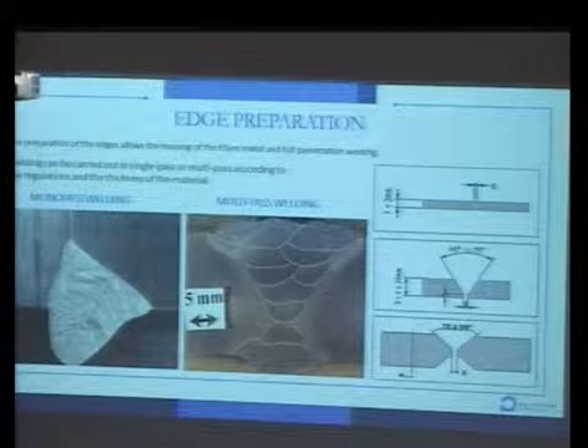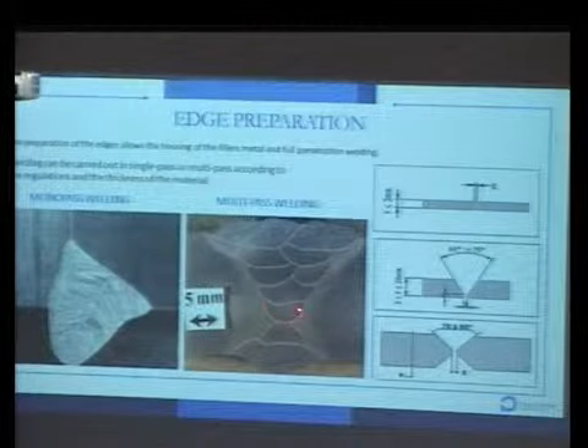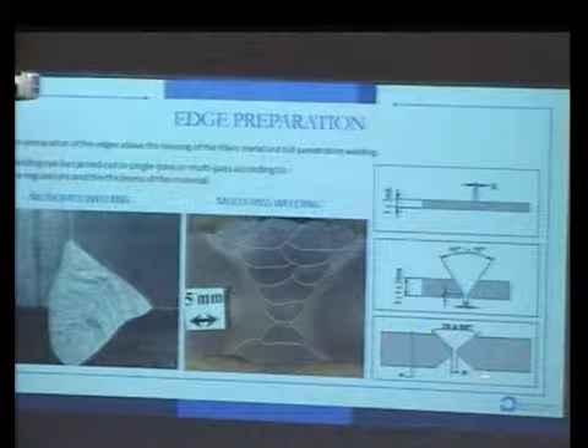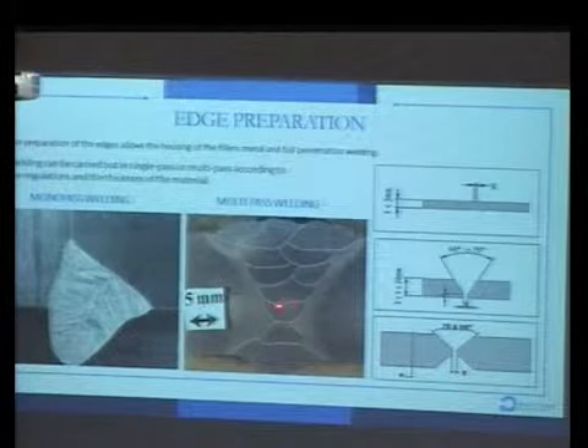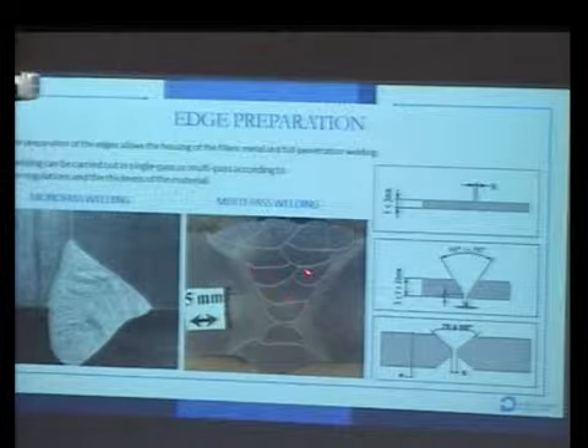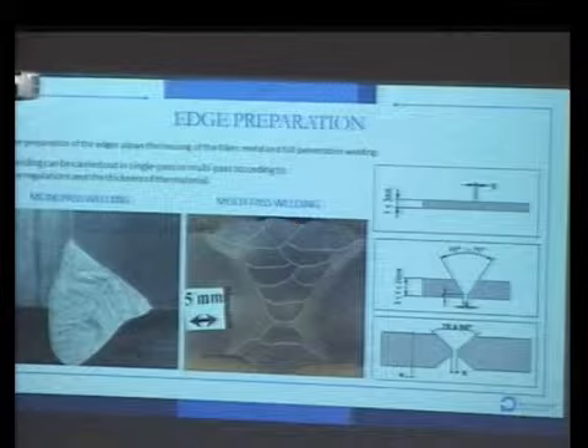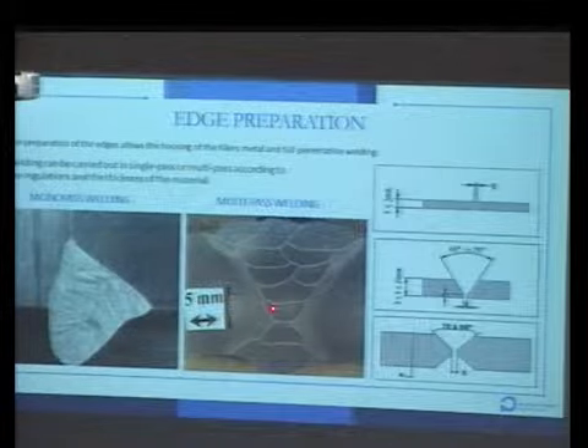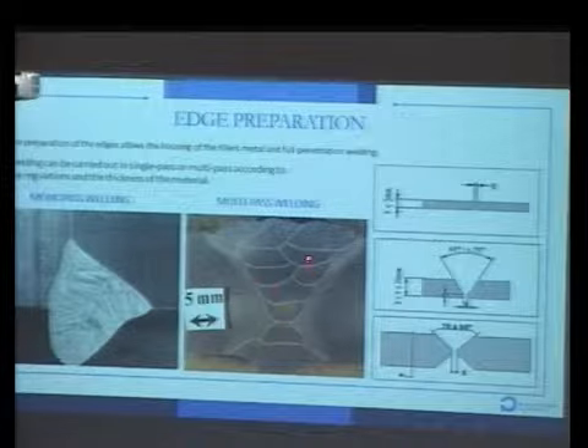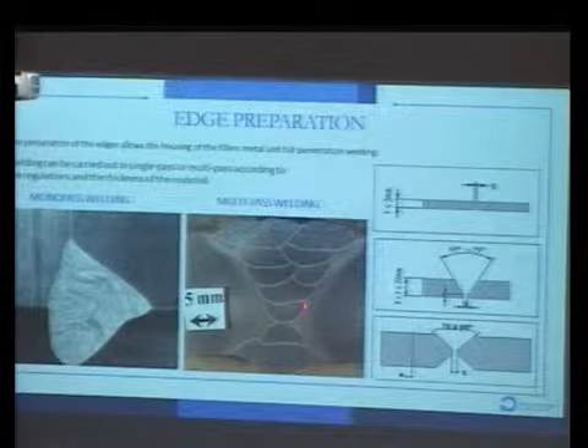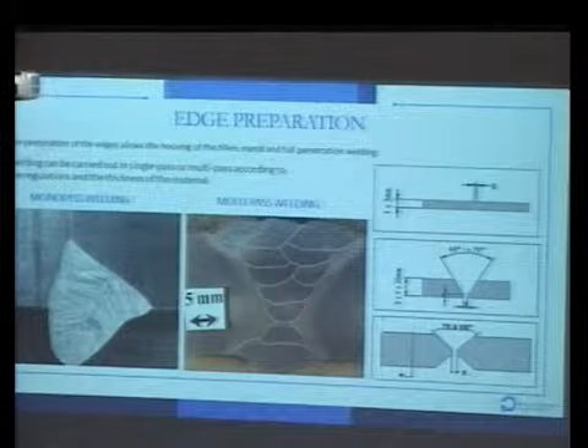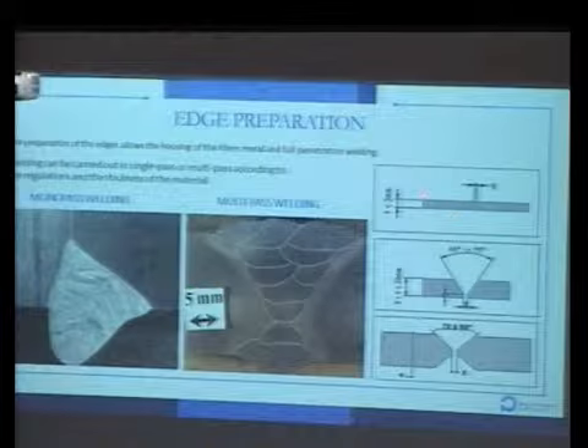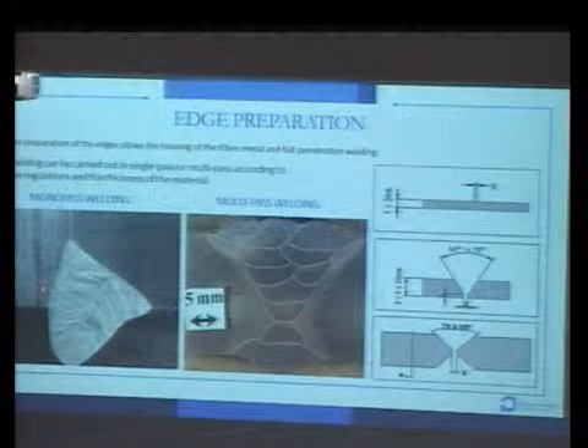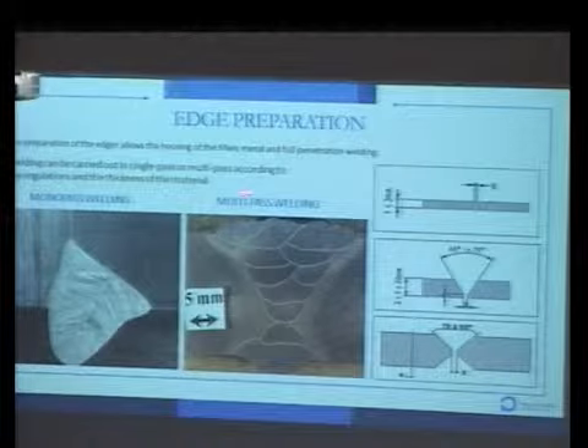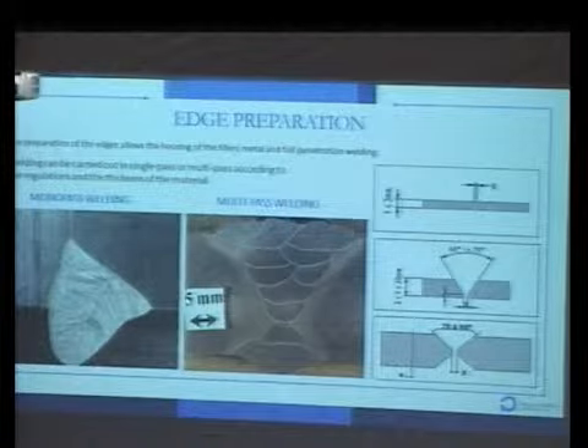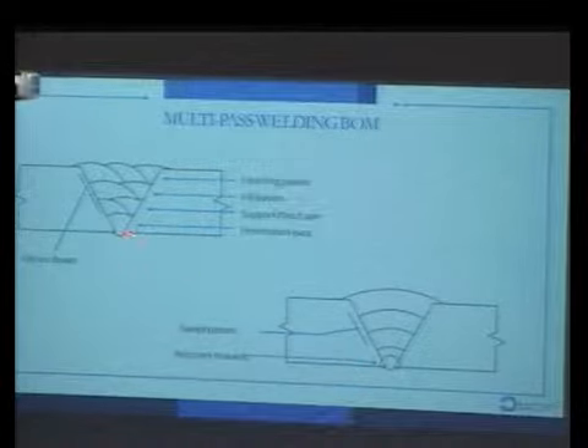For example, here you have a root here. The preparation was like that. You make a root here, and then we make different passes to fill it. In this case, the root is here, and you have here 1, 2, 3, 4, 5, 6, 7, 8. 8 passes on one side and 2 passes on the other side. If you are thinner than 3 millimeters, one pass is enough. We talk about monopass welding or multipass welding. That is an example of penetrant roots.